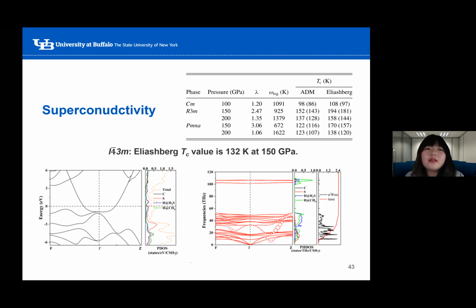So we estimated the superconducting properties for these structures. All of these structures are metallic at their stable pressures, and using R3m as an example, the metallicity is mainly due to the trihydrogen sulfide frameworks. The methane molecule barely contributes anything, and there's very obvious hydrogen and sulfur character, and it's very indicative of hybridization.